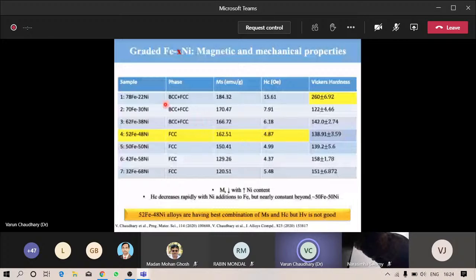Here are the magnetic properties along with the Vickers hardness for all these samples. We have a good saturation magnetization and low coercivity value, but the hardness is not good for that particular composition. So we need to compromise: either we have good magnetic properties but bad mechanical properties, or the other way around. As I mentioned in my introduction slides, it's very challenging to get both good magnetic and good mechanical properties in one sample.